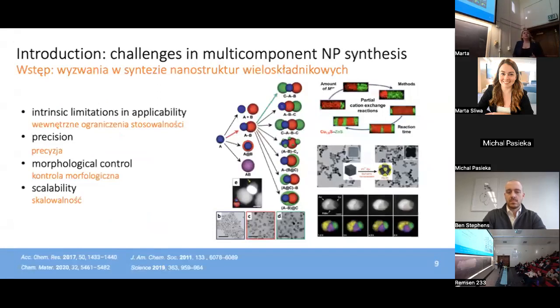So although many examples of multi-component nanoparticles exist, with those that I just highlighted only representing a small fraction of what's in the literature, the methods used to make them are not without their limitations. One of the major limitations is that one method might not necessarily be applicable to a broad range of materials, or it's only applicable to a small set of precursors that you can use to make these structures. Secondly, some of these methods just aren't really good at making precise interfaces or junctions between the building blocks that make up that multi-component structure at the end. Some of these methods also aren't good at controlling the size and shape of the products that they yield. And lastly, a lot of the methods just don't make enough of this product to be industrially relevant or scalable to the point that you can use it in a larger application.